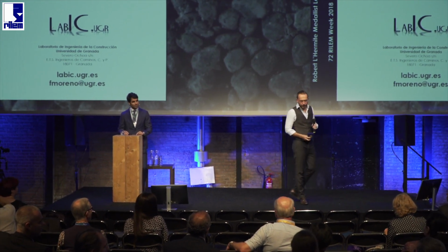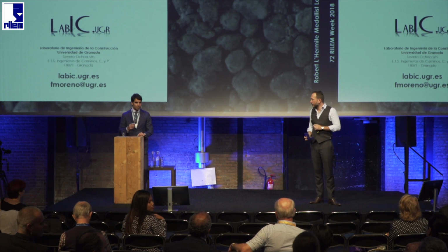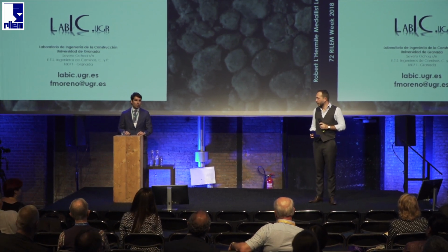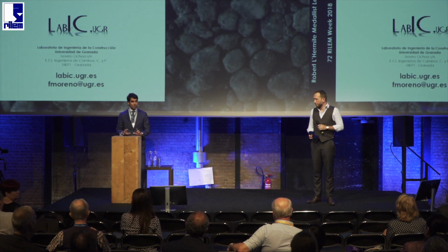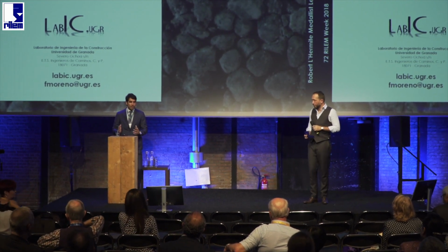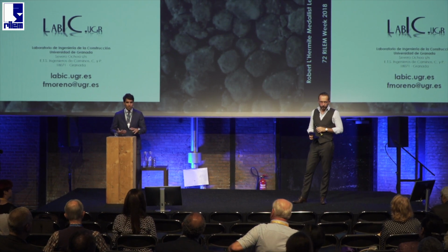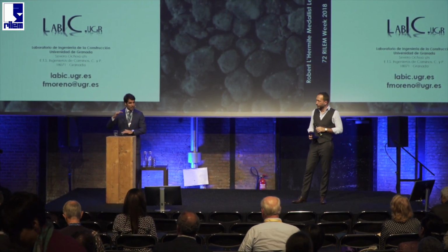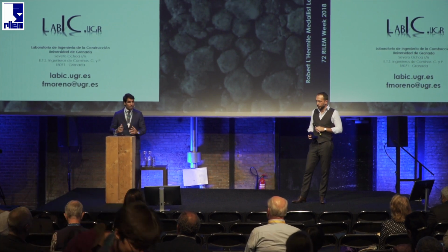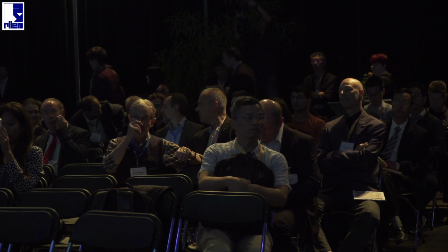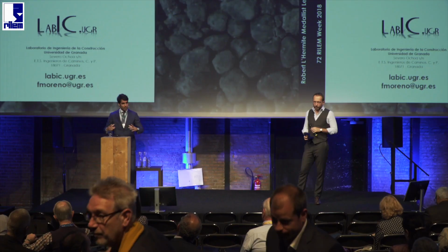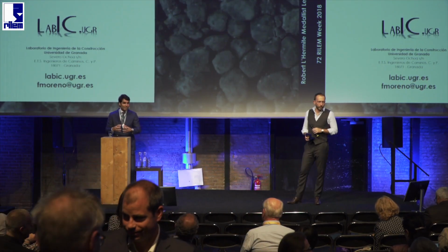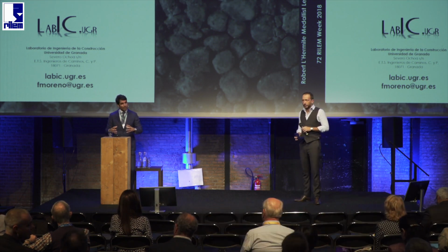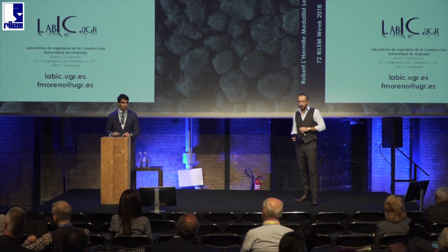What is the size effect? The size effect can be controlled because the specimen does not always have the same size. You can test different types of specimen, from a complete pavement section to a small core taken on the road. The specimen will be manufactured based on the maximum size of aggregate, so we control it that way. The distance between the plates can be varied, so the volume where we study the mechanical performance of the material varies as a function of the size of the material used inside that volume.